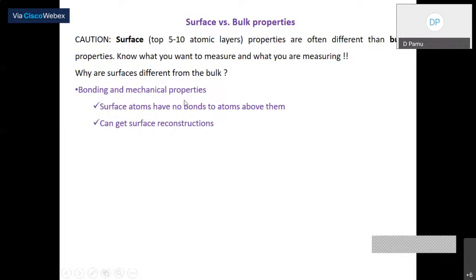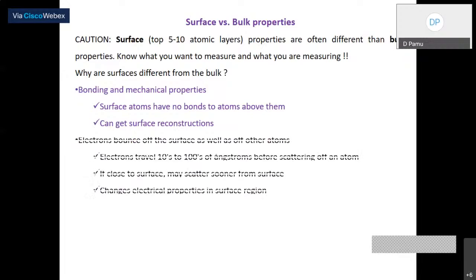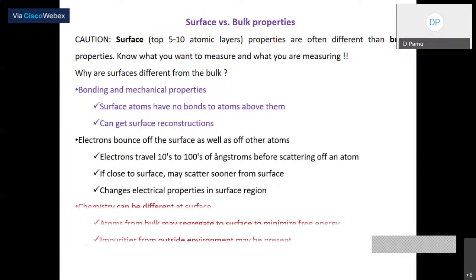We can get surface reconstructions. That means my surface can be modified if I give a high energy tool, so the arrangement of atoms is possible. Electrons bounce off the surface as well as off the other atoms, because they are not properly bonded. Electrons travel tens and hundreds of angstroms before scattering off an atom. Close to the surface, many scatter sooner. That is what changes electrical properties at the surface very strongly. That is where thin films behave differently from bulk.